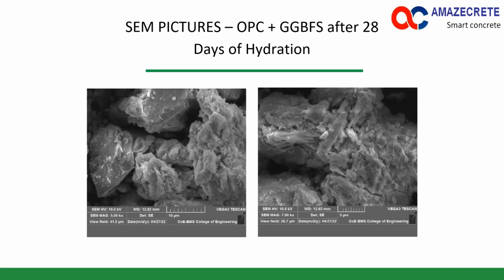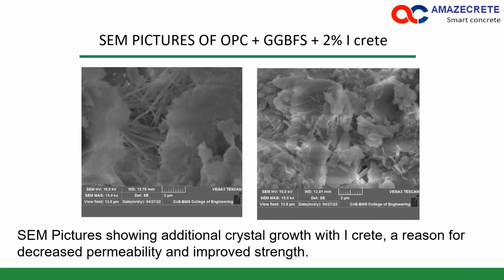When SEM pictures are taken, you can see growth of crystals, which again demonstrates that iCrete works and helps in decreasing the porosity. So the SEM picture shows additional crystal growth with iCrete as a reason for decreased permeability and improved strength.